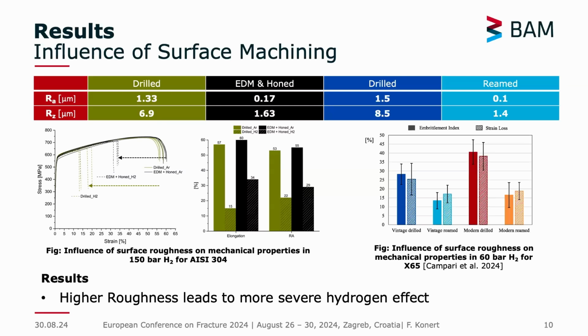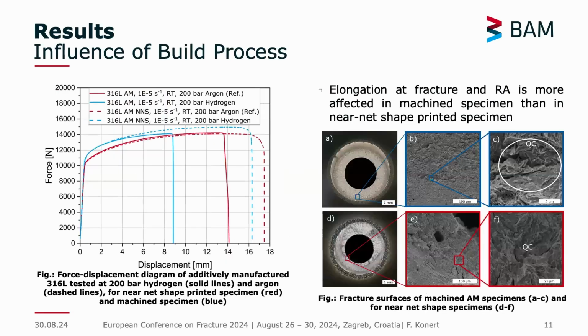We tested the same for two ferritic pipeline steels, one vintage one from the 80s and a more modern one, and we got the same results. Here the manufacturing conditions are slightly different. We have a drilled specimen and a drilled specimen which was afterwards honed. You can see the surface roughness is on the table. The honed surface roughness is quite comparable to the EDM and honed surface roughness, and the drilled ones are also quite similar. As you can see, there are quite big differences in how you produce a hole. So if you want to compare hollow specimens and results from them, you want to keep an eye on this. With this, I want to come to the additively manufactured specimens.